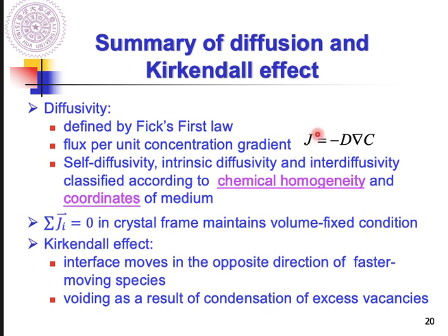So it means the flux per unit concentration gradient. And you can divide the diffusivity into self-diffusivity, intrinsic diffusivity, and interdiffusivity according to the material system and also the observation coordinate of your materials.